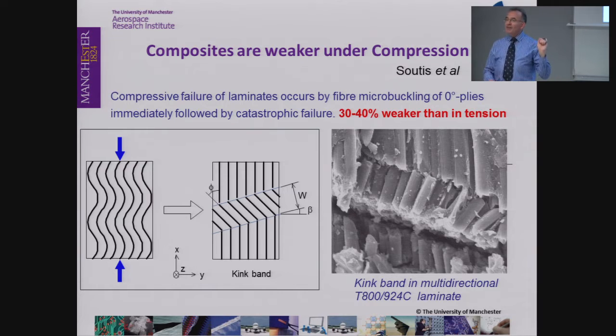So during the curing process, you develop thermal strains which are high enough to distort your fibers. So your carbon fiber of a diameter in the region of 6 micrometers becomes wavy. And when the structure is loaded in tension, the wavy fibers become straight. But when your structure is loaded in compression, the wavy fibers fail in the mode of fiber microbuckling, which is a fiber instability failure mode that takes place at the fiber level. And although the structural engineer has designed his structure to avoid Euler buckling, you can still fail in the form of fiber microbuckling, which then reduces the strength by up to 40%.